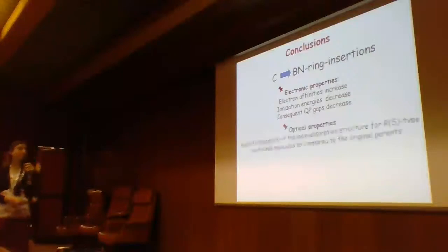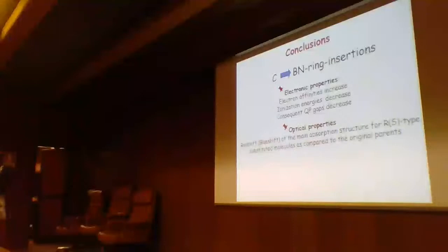Conclusions follow because we have analyzed what happens in the passage from carbon-based molecules to boron nitride ring inserted ones. For the electronic properties, we have found a general increase of the vertical electron affinities, a general decrease of the vertical ionization energies, and also of the quasi-particle gaps. For the optical properties, we have found a redshift of the main absorption structures in the case of ring substituted forms, while a blue shift in the case of the stripe-type substitution, and a redistribution of the amplitude and energy in the UV and in the visible.